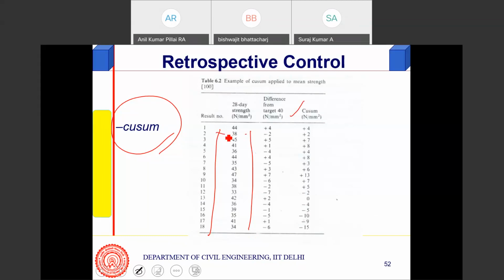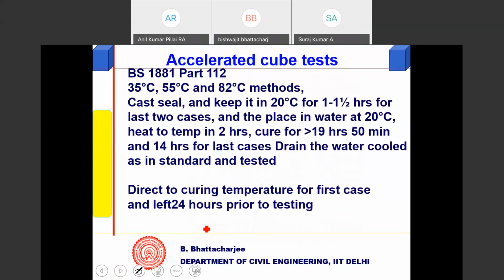So today, the first result you found, the deviation from the target is +4, the next deviation from the target is -2, and the cumulative sum of this goes this way. So 4 minus 2 is +2, and again +5 makes it 7, +8 -4, and so on. And then you can plot this cusum against the result number. For the accelerated test, they have 3 regimes, and it has to be specific to yours. The correlation is not the same.